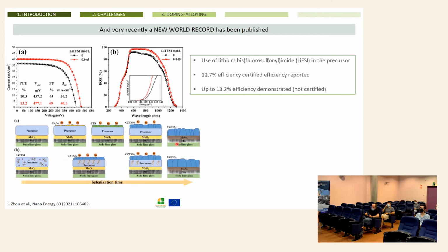Sorry for not explaining the device structure, but normally in a solar cell, you need your absorber material, so your photoactive material, and two selective contacts, one for electrons and one for holes. So the typical kesterite structure, we use soda lime glass as substrate, very cheap substrate. Then molybdenum is the back contact. And we are very lucky because when you synthesize kesterite, in the way I explained before, using a selenium or a sulfur atmosphere, naturally molybdenum selenide or molybdenum sulfide is formed.